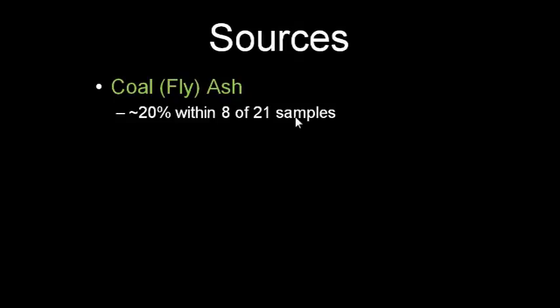So in conclusion, here's what we're thinking in terms of the sources of the microplastics that we're finding in the Great Lakes. Some of the samples that we took in 2012, we refined our method, so we shouldn't be getting this ash in as we're processing our samples for 2013. But for 2012, some of the particles that we found that were initially identified as plastic within our samples were actually found to be coal ash or fly ash. But the vast majority of what we're finding is coming from essentially consumer products.